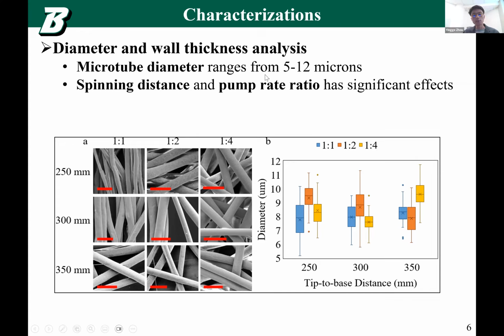So for the diameter range from 5 to 12 microns, even though it's not 1 to 10 microns compared to our native human capillary vessels, it's pretty close. It's usable. We can also fine-tune it to make it a little bit smaller.